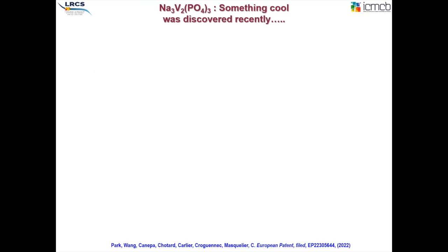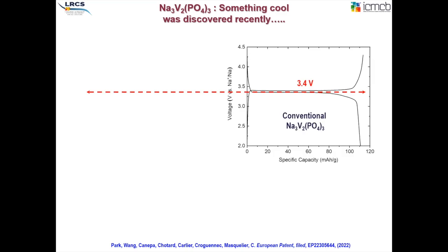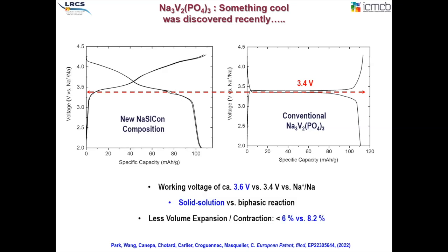we made a nice discovery, I think, together with my colleagues, which we patented and that I'm happy to disclose today. It's that indeed conventional Na3 V2 PO4 three times works at 3.4 volt versus sodium. And we were able, by some tricks that I cannot completely reveal today, to increase substantially the operating voltage of this NASICON electrode towards 3.6 volt average versus sodium.